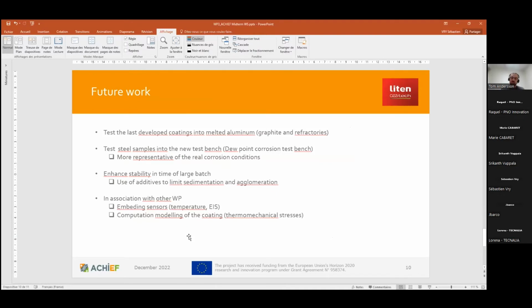The further developments focus on the assessment of the performance of samples that were immersed into melted aluminum. The new dew point test bench, which is more representative of the real conditions, will be used to test coatings in acidic environment. And further development focuses on the use of larger batches, because work has to be done on the stabilization of the formulation. The use of additives is mandatory to limit sedimentation or agglomeration of ceramic particles.